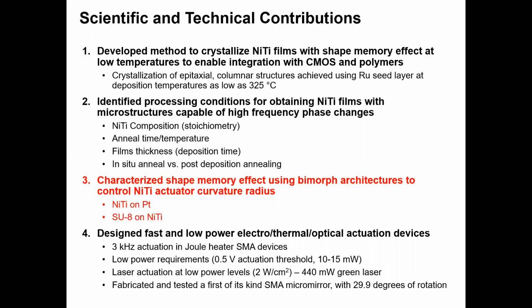So this is contribution 3, and it was looking at fabricating stress bilayer MEMS actuators and characterizing the actuator curvature radius and degree of unfolding due to the shape memory effect. So I utilized 2 main approaches to fabricate these devices. The first instance was NiTi sputtered onto platinum at high temperatures, which resulted in the CTE mismatch induced stress, which was suitable for curling the MEMS actuator after release from the substrate.